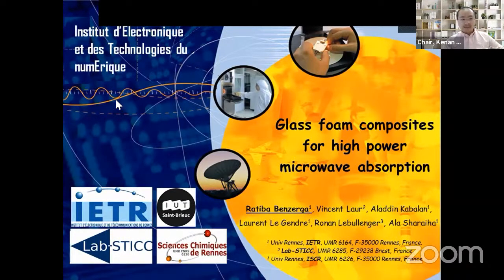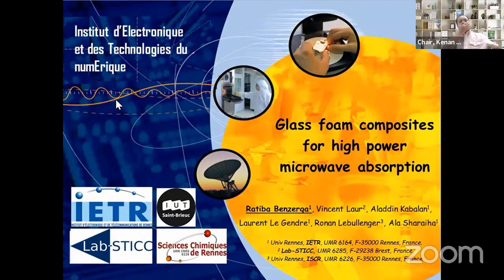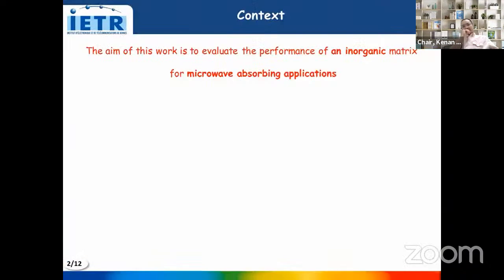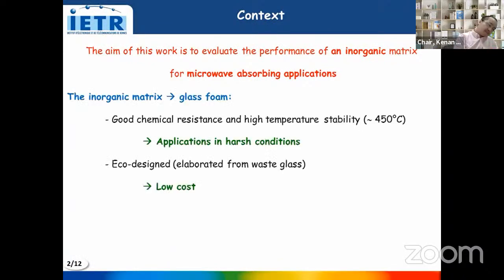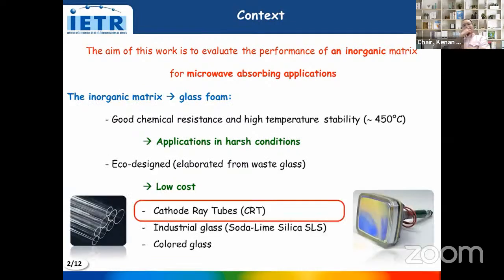This poster concerns glass foam composite for high power microwave absorption. The aim of this work is to evaluate the performance of an inorganic matrix for microwave absorbing application. Inorganic matrices present good chemical resistance and high temperature stability. They are also eco-designed here because they are elaborated from recycled waste glass.